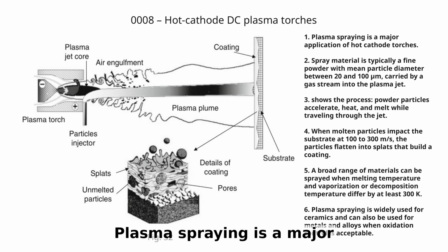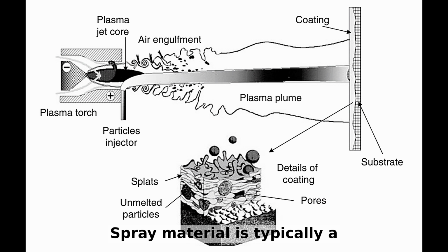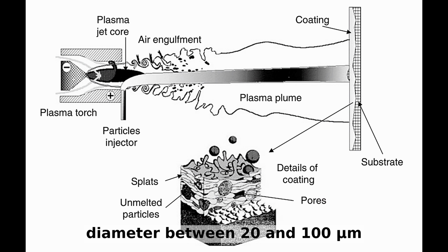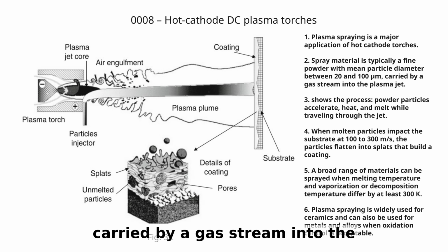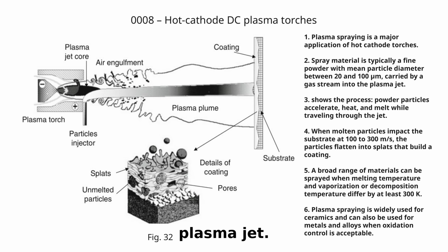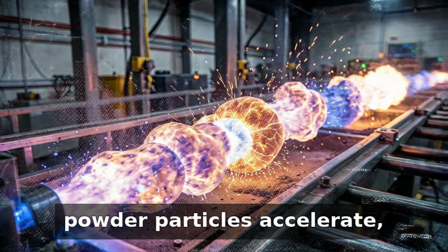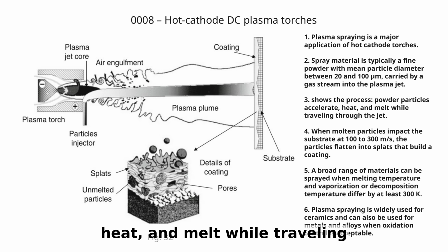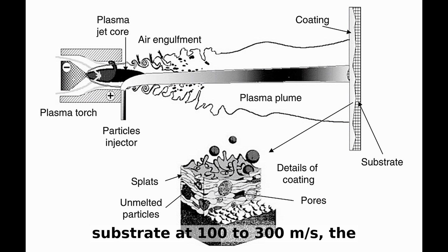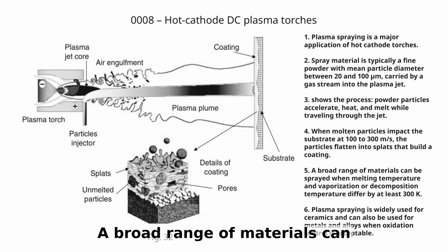Plasma spraying is a major application of hot cathode torches. Spray material is typically a fine powder with mean particle diameter between 20 and 100 micrometers, carried by a gas stream into the plasma jet. Figure 32 shows the process. Powder particles accelerate, heat, and melt while traveling through the jet. When molten particles impact the substrate at 100 to 300 meters/s, the particles flatten into splats that build a coating.